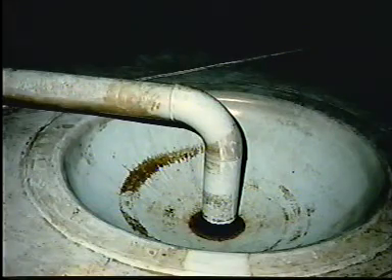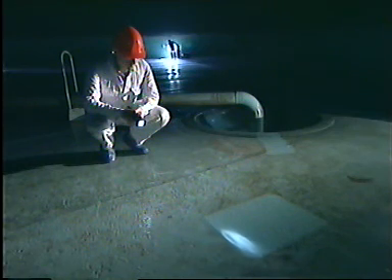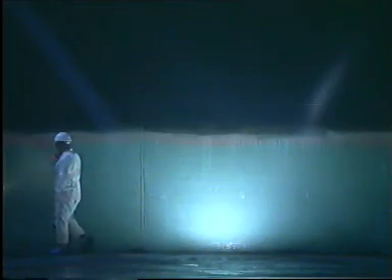Fina examined several solutions, finally deciding to coat the tank bottom and lower walls with the solvent-free lining SigmaGuard CSF. In May 1996, the tank was drained, cleaned and inspected. An exciting moment for the owner, applicator and coating supplier. This area on a heavily pitted plate was cleaned for inspection. Close-up examination showed how, during application, the coating had penetrated and sealed the pits. Almost 5 years immersion in gas oil and acidic water had had no effect whatsoever on the integrity of the coating.